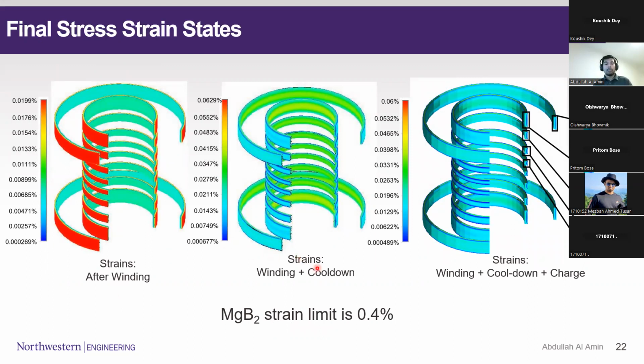And after winding, cool down, and electromagnetic excitation, which I, in short, call charging, I can look at the entire scenario of the stresses and strain, and then check against the strain sensitivity of the magnesium diboride. On a smaller scale experimental study, we already know that the magnesium diboride material I'm working with can only withstand 0.4% of tensile strain. So by no means can I go beyond 0.4%. In fact, if you consider a certain engineering safety factor, our limit was 0.2%. From this analysis, we can see that the strain is about 0.06%, which is good news. That also means we have some room that we can leverage in the operation stage.